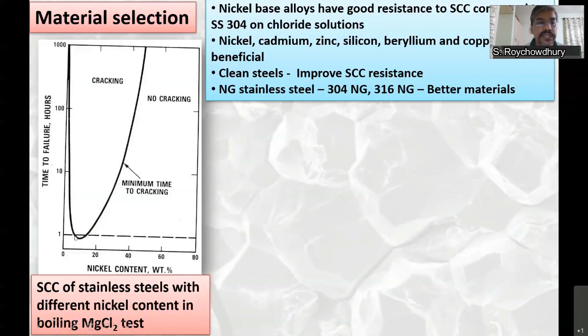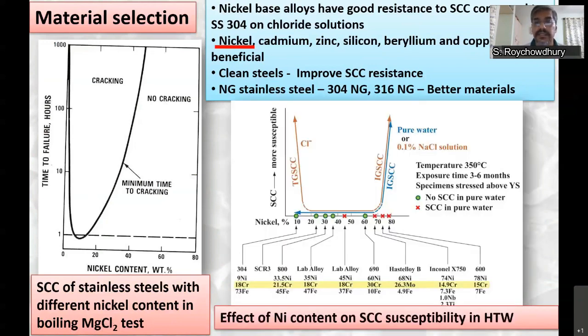If you see, around 8 to 10% nickel gives the minimum time to failure, indicating that the cracking is very fast. This is the alloy composition for SS304. It contains around 8 to 10% nickel. So 304 will crack very quickly in boiling magnesium chloride. So nickel concentration, as I told you, is very important. This is another curve showing the SCC susceptibility in high temperature water.